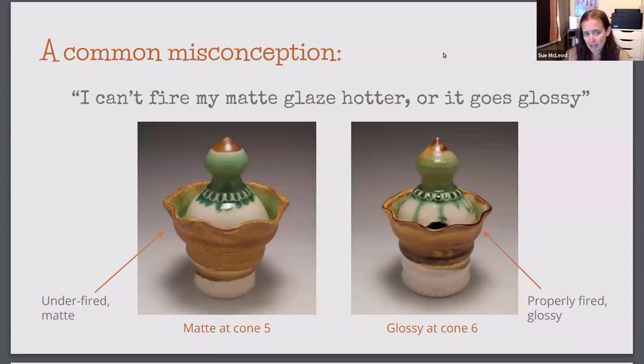A common misconception is that I can't fire my matte glaze hotter or it goes glossy. This is one of the things I believed before I learned chemistry. I had these glazes that gave me such a hard time. They were very runny. They contain a bunch of lithium, and once they started melting, they would just run onto the kiln shelves. So it was like, okay, I can't fire them hotter, because if they're underfired, they are matte. This is cone 5, this is cone 6.